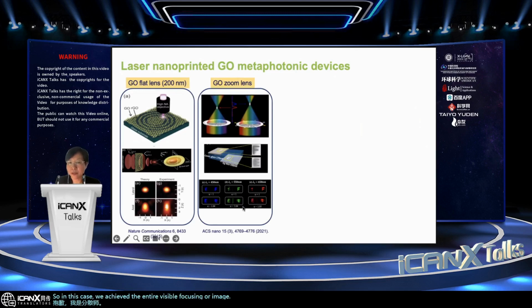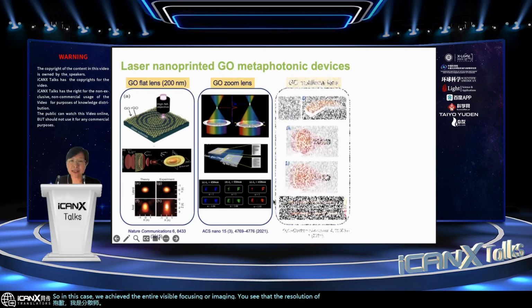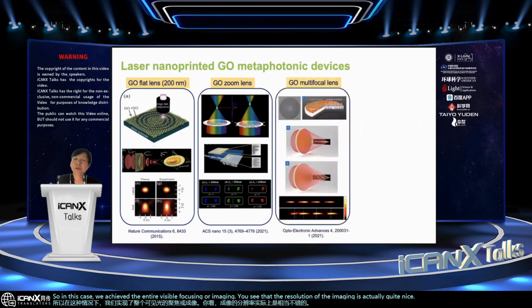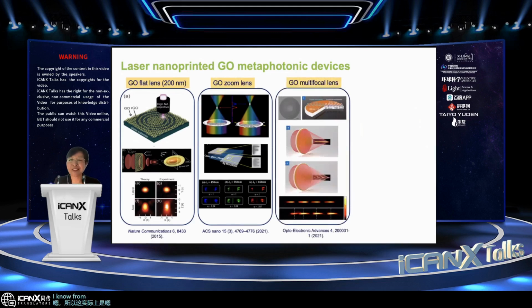You see that the resolution of the imaging is quite nice. So this kind of initiated the research, because we can achieve the refractive index change. That means the phase change. And in the meantime, the extinction coefficient change means the amplitude change. So if you are able to control these two parameters together, you are able to fully control the wavefront design.